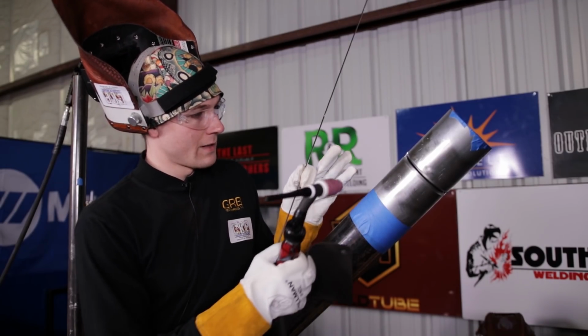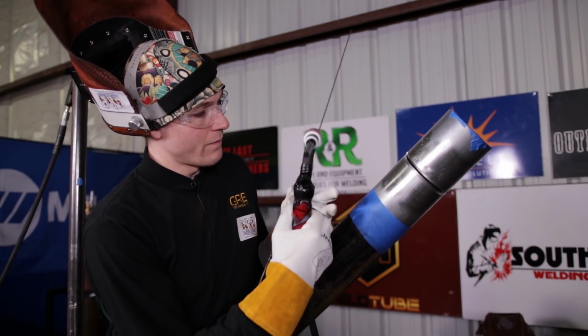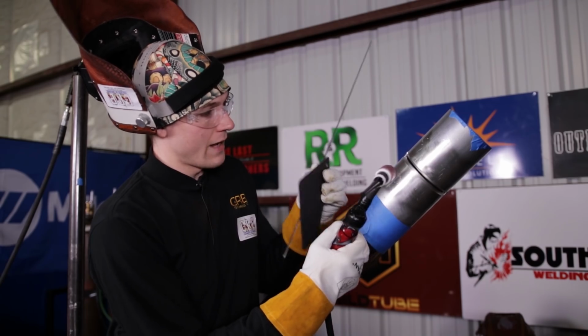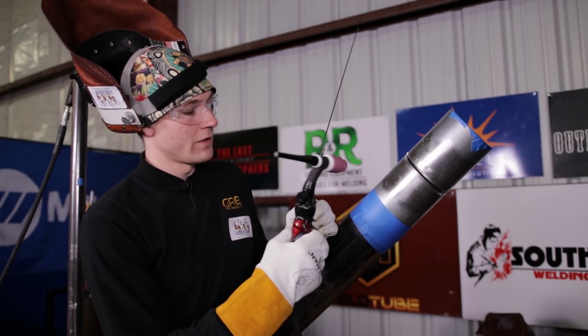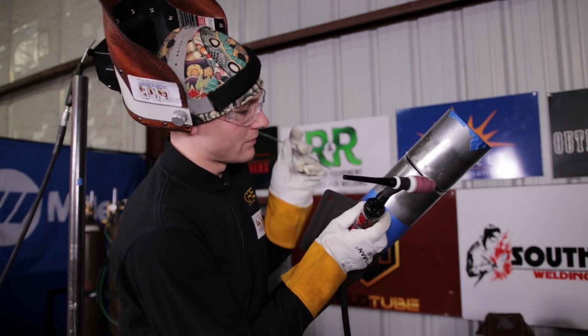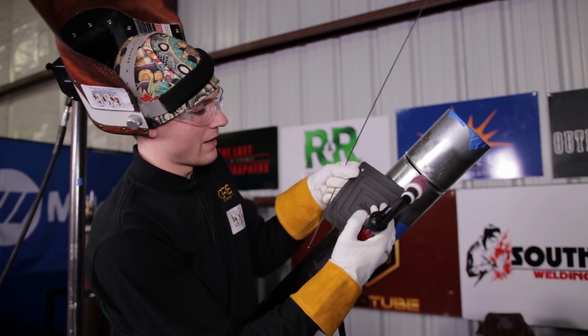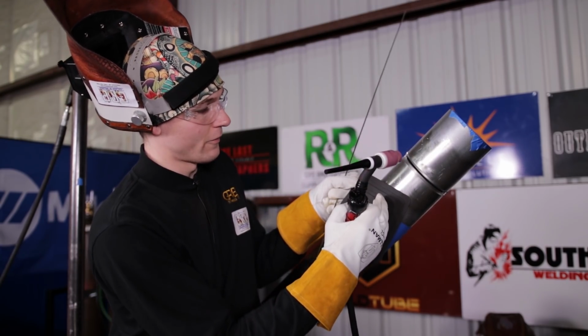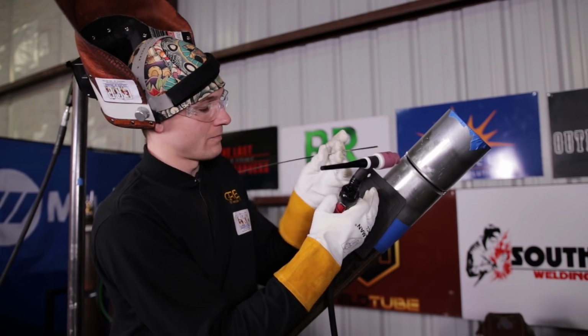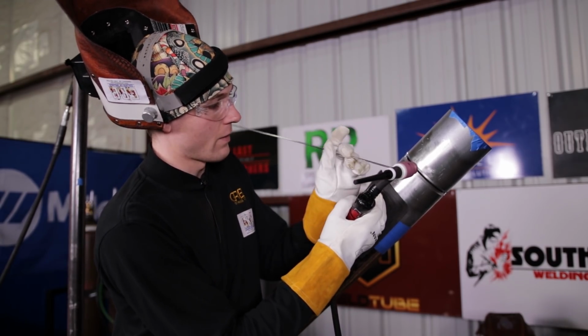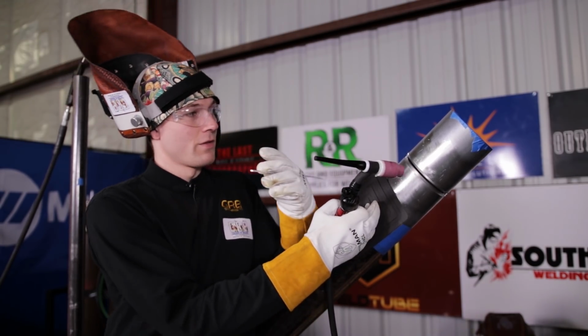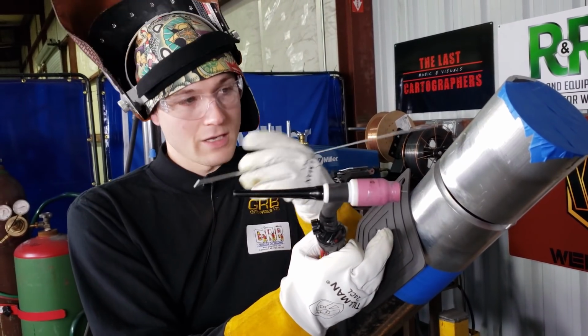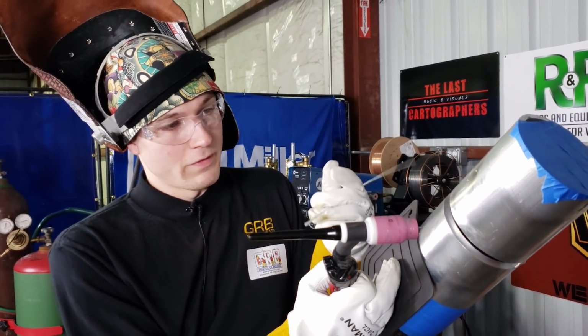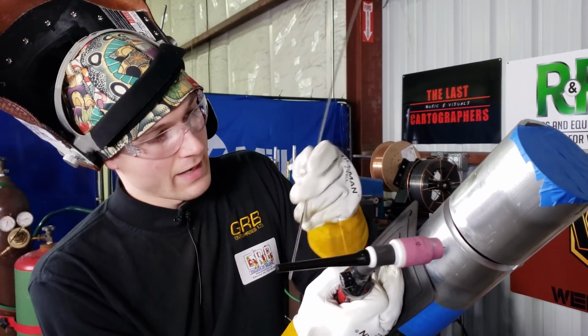Okay, so basically when it comes to feeding, you have to be very precise when you open the keyhole, when you add filament metal to the material here. So I'm going to hold the TIG torch perpendicular, but I'm going to have a pad because this material is going to be at 250 degrees Fahrenheit when I do the root pass, and I'm going to heat it up to about 400 degrees Fahrenheit when I do the rest of the passes. It just helps with the flow and the puddle and breaks down the material that I'm welding on and removes all the oxides. But essentially I can feed it.